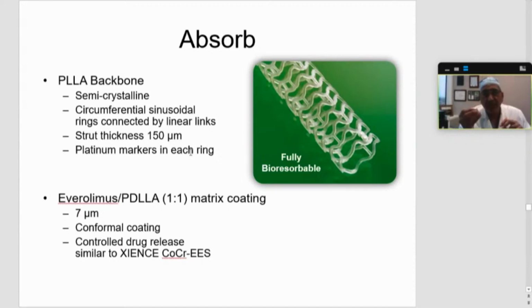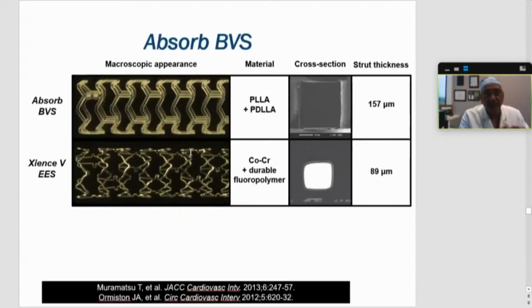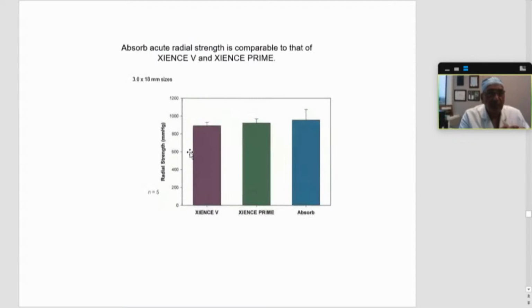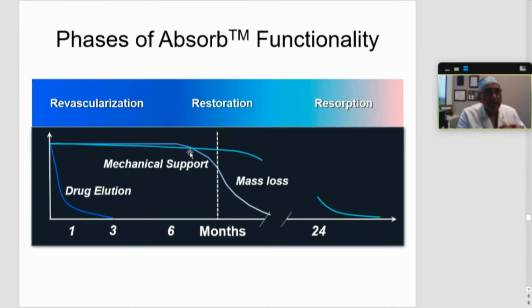The drug is everolimus. It is coated with a PDLLA 1:1 matrix coating, about 7 microns in thickness. It is conformal all around, and there is controlled drug release similar to the Xience cobalt chromium everolimus stent. This is a photograph of Absorb versus Xience. Obviously, it clearly stands out how thick the Absorb bioresorbable vascular scaffold is compared to Xience. But I think those attributes of the stent strut in the first generation iteration were very important to maintain radial strength. And as you can see, there is no compromise on the radial strength of Absorb versus the Xience platform.